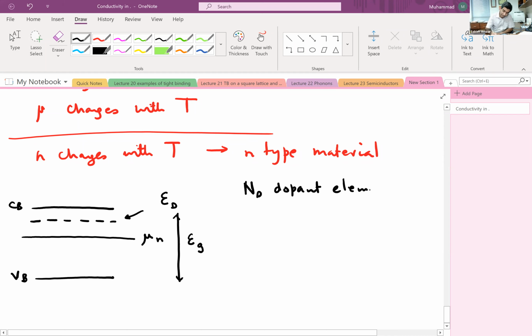This is the number of impurity atoms I put in. And each one of them is donating one electron, by the way. One electron, remember that. So it's a pentavalent impurity. And those extra electrons sit at an energy slightly below the edge of the conduction band. And this is, I mentioned in the previous lecture, 0.1. It's actually 0.03 electron volt. It's even smaller than 0.1. It's of the order of 30 milli-electron volt. And the thermal energy is 25 milli-electron volts, by the way.